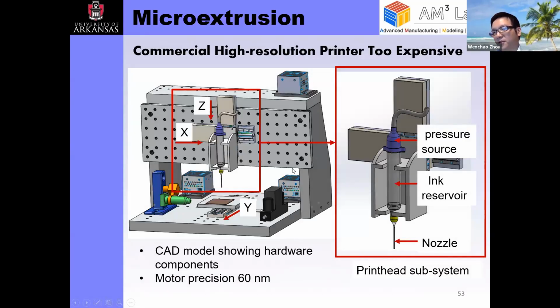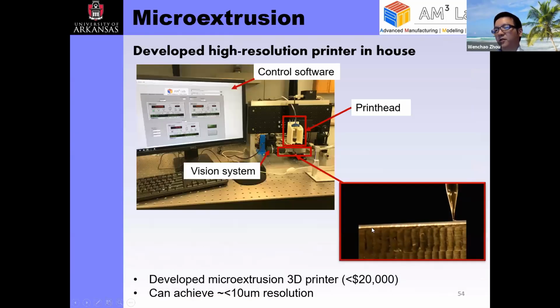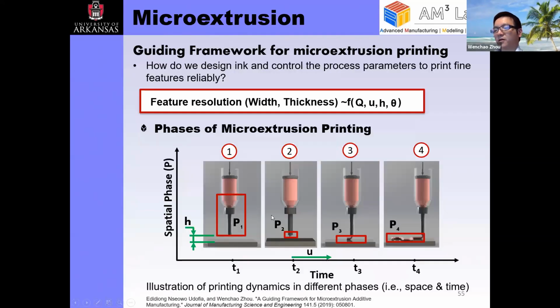And this is the printing stage we developed with super high precision motors of 60 nanometer resolution with very fine nozzles, single digit micron nozzle sizes, and with a pressure source of about 150 PSI from our lab to push the liquid out in order to print. So this is a constructed system, and this is the printing process. You can see this is a pulled glass, which forms a very fine nozzle to push the liquid out and to print. And we're able to achieve less than 10 micron printing resolution, with a budget of less than $20,000, which would cost you about $100,000 if you buy it from the market.